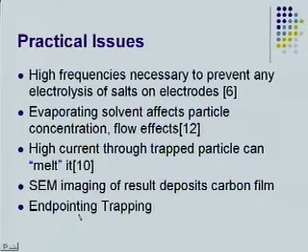And then as we've seen, you have high current, which can sometimes melt. If you apply too high a field, you can actually melt a colloid, or you can melt a junction while you're doing this. And then also, since these are so small, you have to use SEM or some other technique